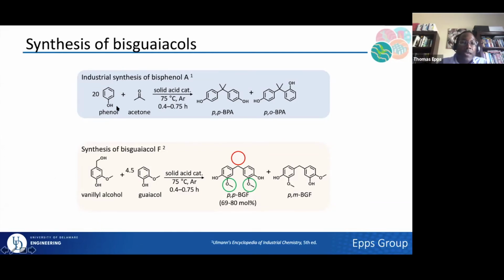The way that we thought about that was, here at the top in the blue is one industrial process for the synthesis of BPA. Now in the bottom, this is basically a synthesis of our bis-guaiacol F. What you can see here is we've got this vanillyl alcohol that we get from lignin, and the guaiacol we get from lignin. The key thing that I want to mention is that we use the same solid acid catalyst. In this case, we can use Amberlyst 15. We're developing some new catalysts as well. We can do this at the same temperature, same time. So essentially you can drop this into the same reactor.